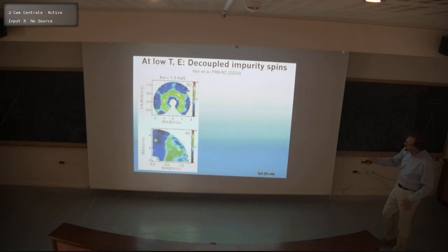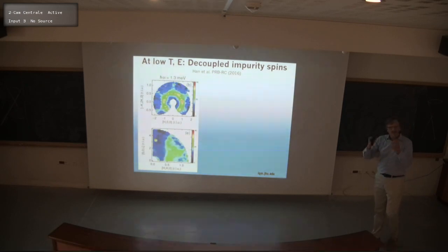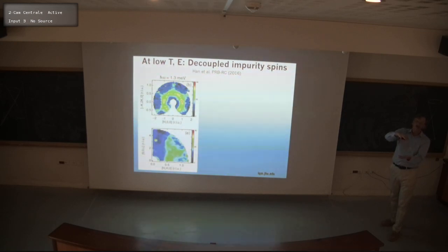What I've shown you down here that wasn't in the previous graph is the momentum dependence of the scattering with the in-plane momentum and the perpendicular-to-the-plane momentum shown. What's important is that there's no dependence of the scattering on momentum perpendicular to the Kagome plane. That's what you should expect in a quasi-two-dimensional magnetic material. The planes are not talking to each other at all, so there can be no momentum dependence in the L direction. We see this scattering at higher energies, and we believe it arises from the individual Kagome layers. Okay, now why am I showing all this?